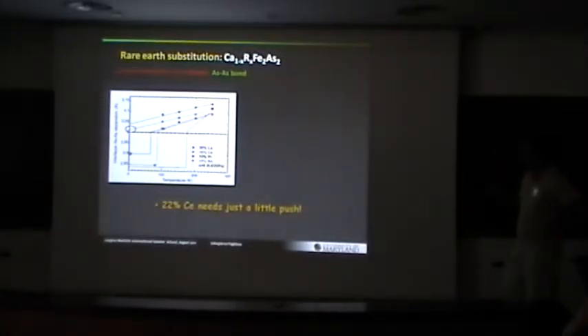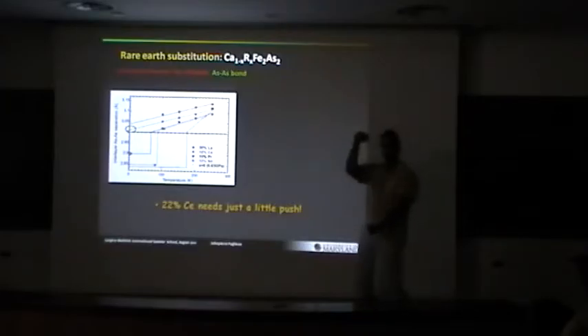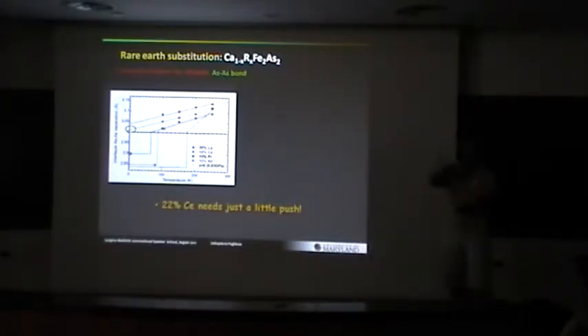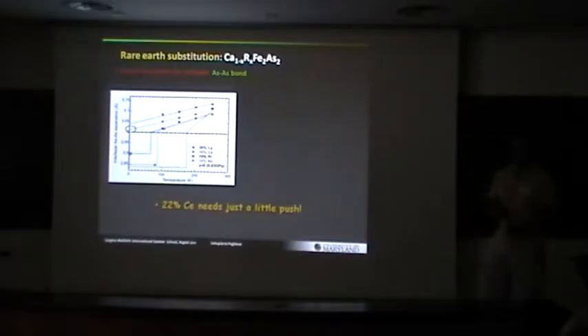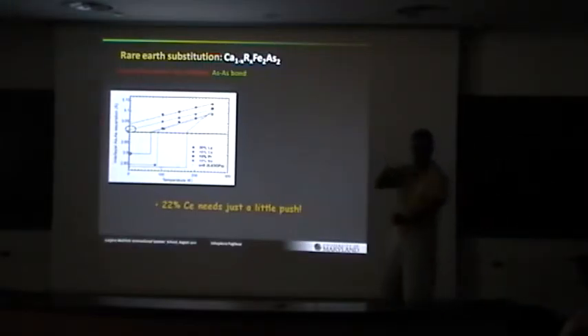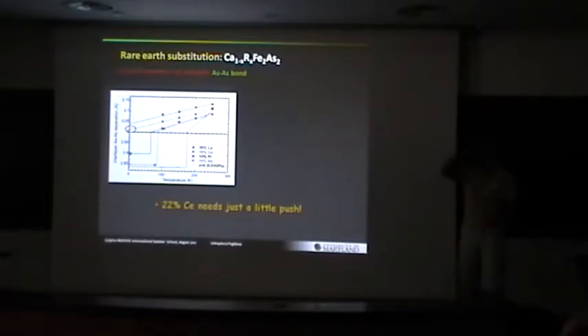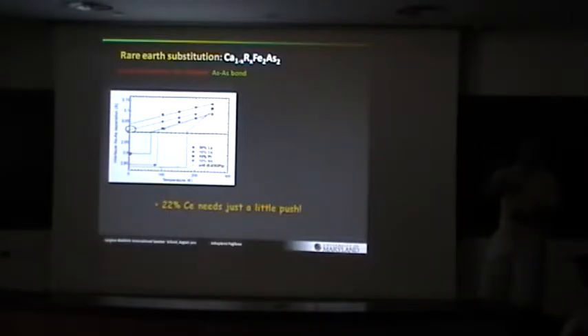You can see that basically the samples that undergo this collapse hit this 3 angstrom line. So this is basically the magic number. Once these arsenic atoms are 3 angstroms apart, they decide to bond, and the collapse occurs. If that doesn't get to 3 angstroms, like in this case here, you do not undergo a collapse, but they're still close to collapsing. It's like an anharmonic effect. They're pulling together, the unit cell is holding them apart, and so that's what I think causes the strong thermal expansion. Yeah. So in the standard 122s, the barium, the strontium, etc., they're much larger than 3 angstroms apart? Yeah. Thanks.